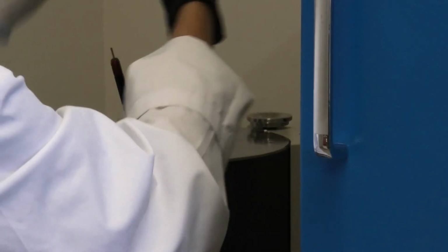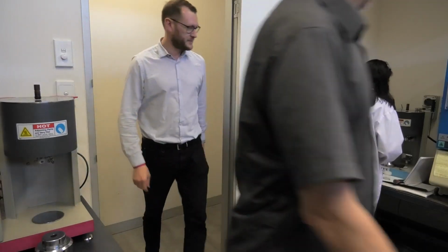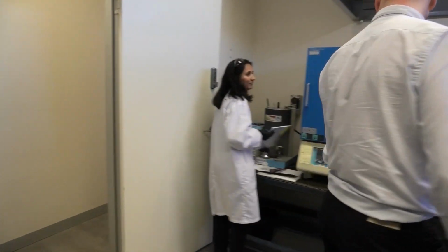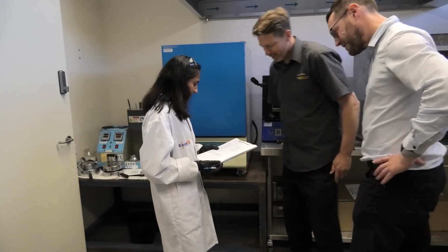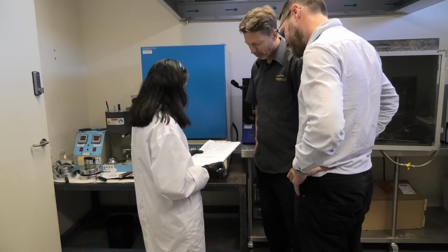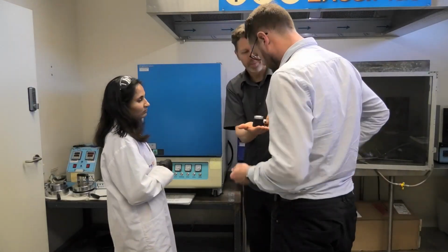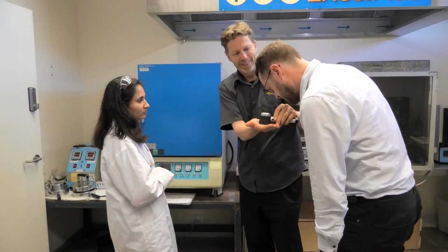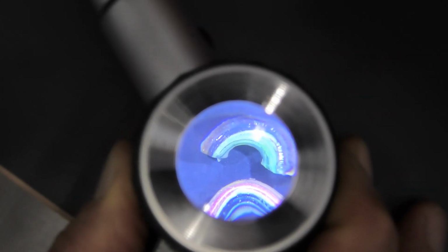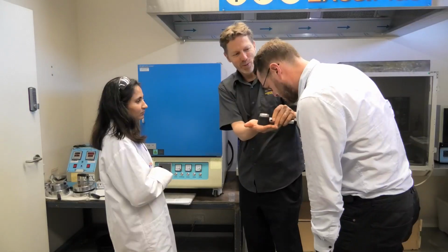For polyethylene to be used in road base modification, it's got to be compatible with the bitumen, and it's got to have a similar melt rheology, a similar flow property to the bitumen. And hence the melt flow index tells you about its flow properties when molten. It'll tell you how well it's going to blend and how well it's going to disperse. And those factors are critical to get a nice uniform mix.